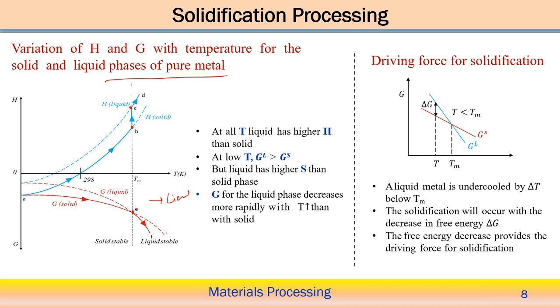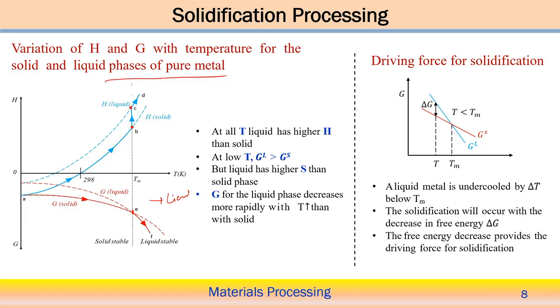So therefore above the melting point temperature, the Gibbs free energy of the liquid phase is lower than that of the solid phase. So here the liquid phase is more stable as compared to the solid phase above the melting point temperature, and that we can see from the Gibbs free energy curve. But at low temperature, below the melting point temperature, we can see the Gibbs free energy for the solid phase is lower than that of the liquid phase. So that's why the solid phase is more stable below the melting point temperature.